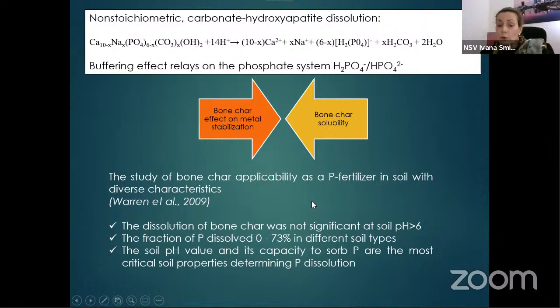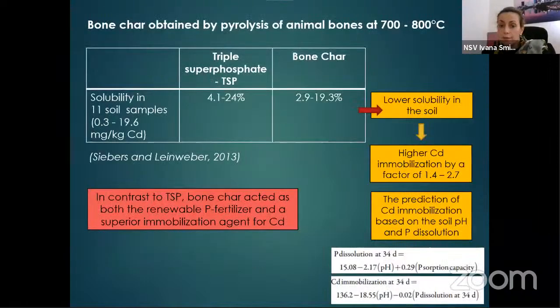And a study on bone char applicability as a phosphate fertilizer in the soils of different types has revealed that the dissolution of bone char varies from 0 to even 73% in connection with the pH value of the soil, and that the dissolution is not significant in the soil that has a pH value higher than 6. So acidic soils are more prone to increase the reactivity of bone char and to induce higher immobilization effect.